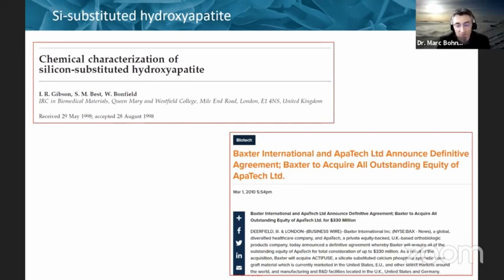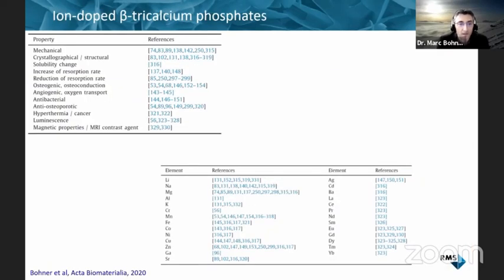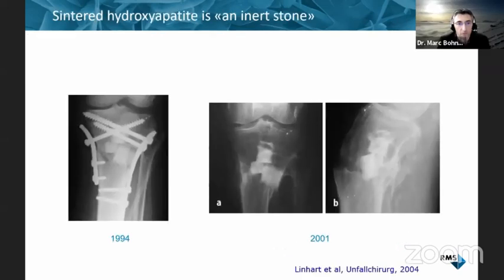So there's been a huge interest in this doping, not only with silicon, but also with strontium, with magnesium, with sodium, and so on. And in 2020, I published a review article on beta-TCP, where I indicated in these two tables on the top the reason why you would dope, in that case, a beta-tricalcium phosphate. Some are for biological reasons, but also for other reasons like luminescence, and the number of ions that have been taken for ion doping. This gives an idea about the interest from the research community for these approaches.